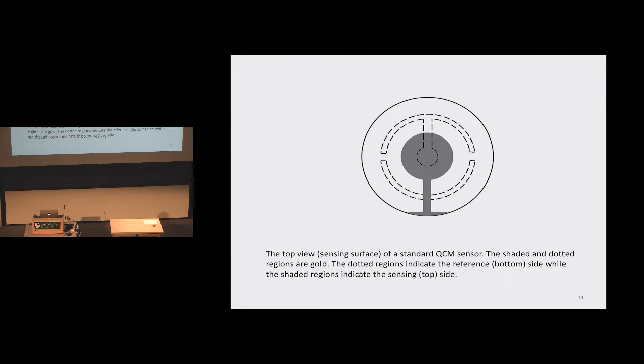The top view of the most common device made on this quartz substrate is the standard QCM, which is often referred to as a quartz crystal microbalance. That's what QCM stands for. The shaded and dotted regions are gold. This is on the top. These are on the bottom of this sample. And believe it or not, the actual electrode goes around the side of this sample to connect to the electrodes on the back side. So what you have here can be excited on the back side of the crystal with an RF signal, and it then sets up a transverse shear mode that propagates from the top face to bottom face of this material.